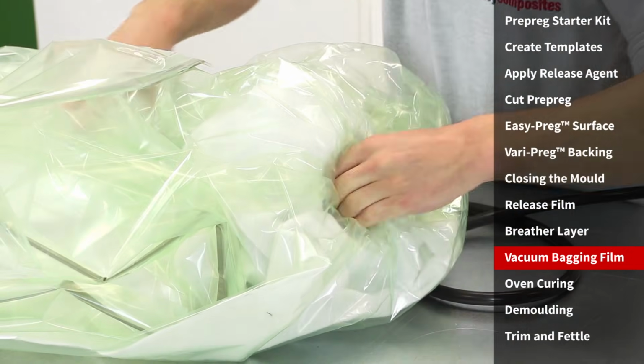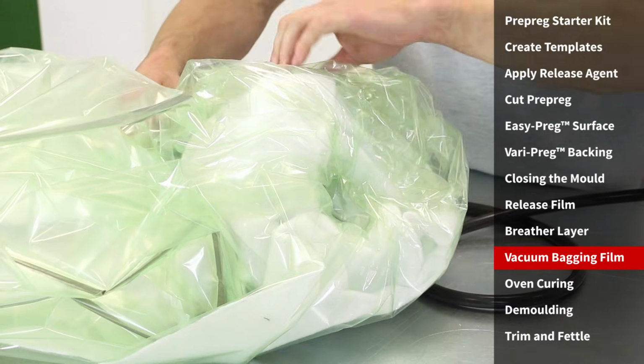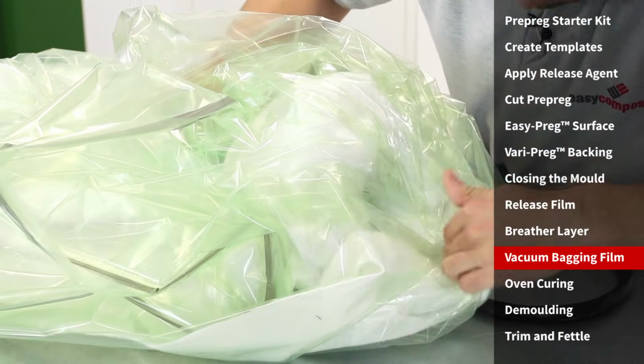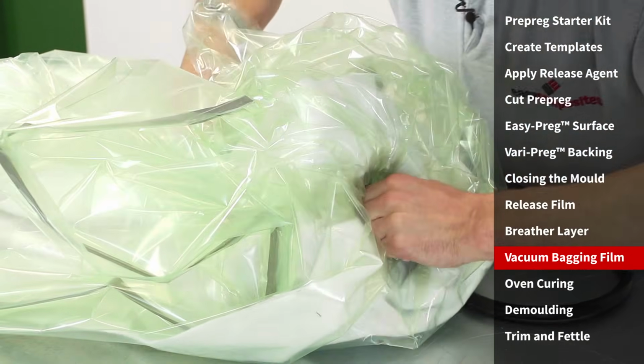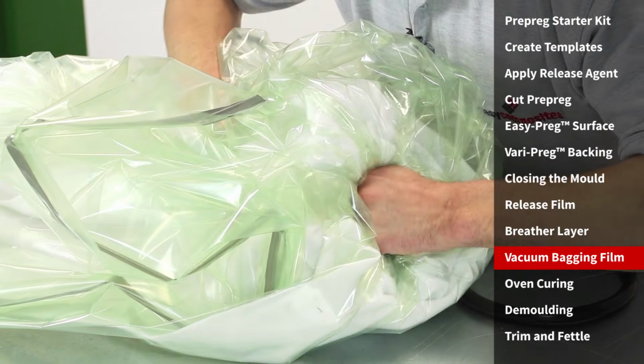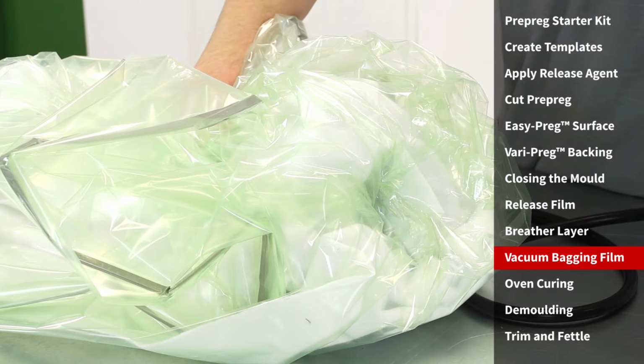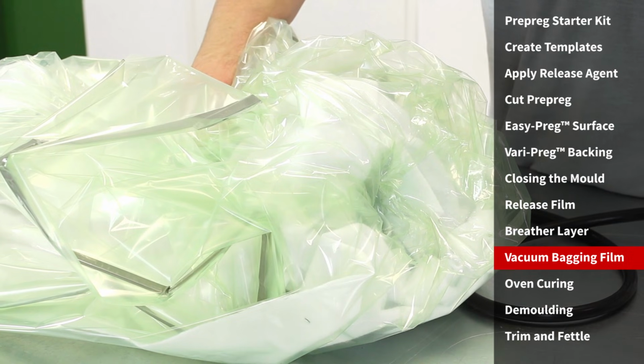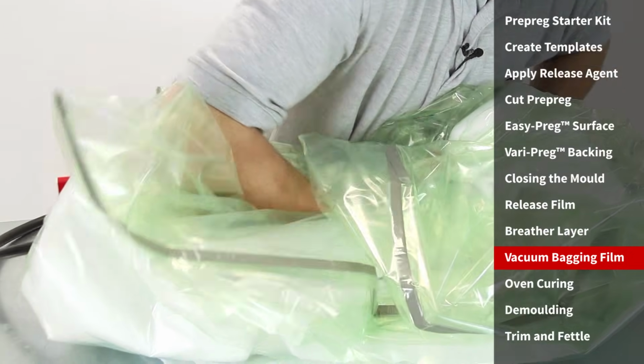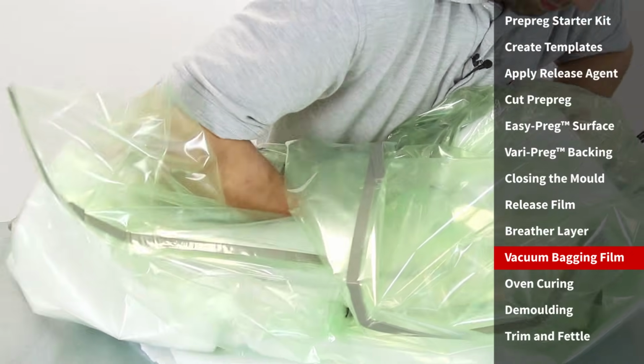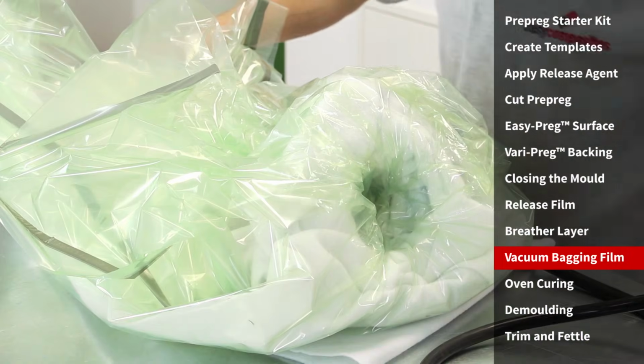Being such a complicated shape, it's perhaps a little difficult to see exactly what's happening here as we first begin to pull down the vacuum. Essentially, what I'm doing is feeding all of the surplus bag inside the mould through the aperture in the base, and then pushing this surplus of bag up into the neck of the airbox, whilst at the same time pushing more surplus bag into the neck from the other side.